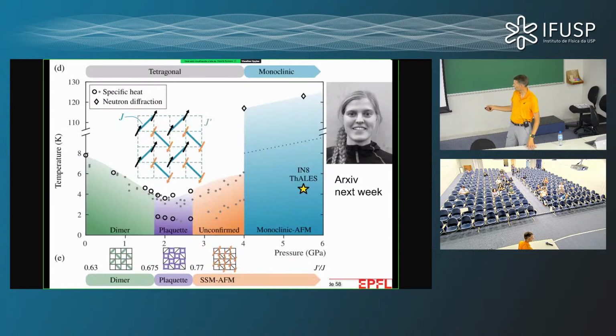Basically, okay, this is not super precise, but it's essentially that. You need 1.8 gigapascal to make the transition between the dimer and the plaquette phase. You need 4 gigapascal to go into the monoclinic phase. Now you will see here, unconfirmed, and in fact, later than Julio's specific heat experiments, there's been a Chinese group who has done similar measurements.